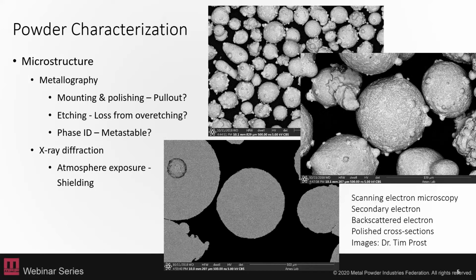If you're looking at larger particles versus smaller particles, your quench rate of those powders is different as they're solidifying during the process. And so you could have different phases or even different metastable phases present based upon how fast those particles cooled. So those pieces need to be part of your characterization, making sure your process is consistent and making sure you're getting the full information that you need for your particular application.